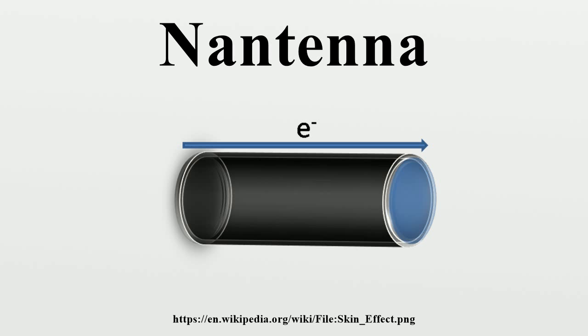Lowering structure resistances also increases the diode cutoff frequency, which in turn enhances the effective bandwidth of rectified frequencies of light. The current attempt to use calcium in the top layer results in high resistance due to the calcium oxidizing rapidly. Researchers currently hope to create a rectifier which can convert around 50% of the antenna's absorption into energy.